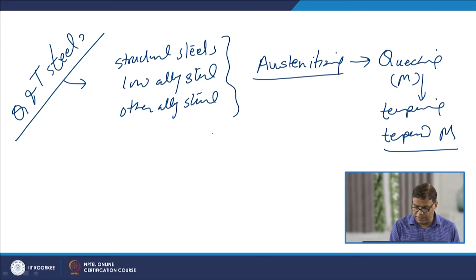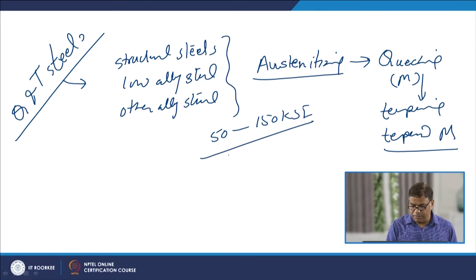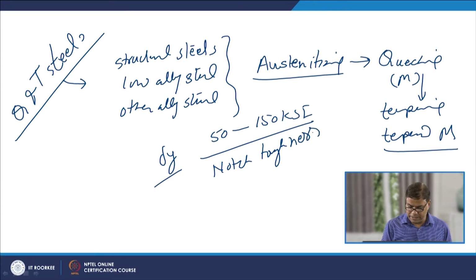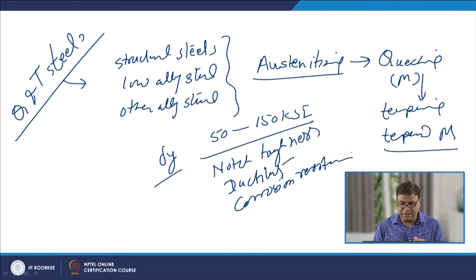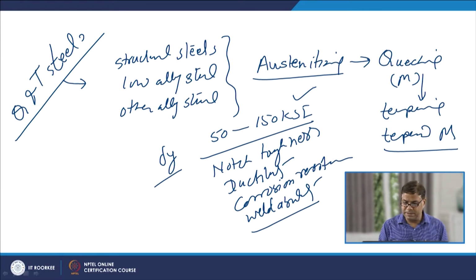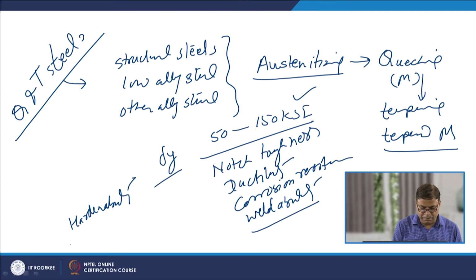combination of the mechanical properties, like yield strength can range from 50 to 150 KSI. Apart from the yield strength, it also possesses very good notch toughness, good ductility, offers very good corrosion resistance, and the carbon equivalent due to the low carbon content is such that the weldability is also good. But since the strength is high and the presence of alloying elements is also there in these steels, hardenability of the steel must be kept in mind while talking about the weldability of the Q&T steels.